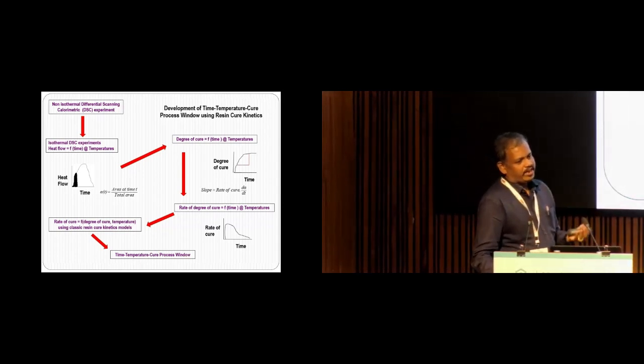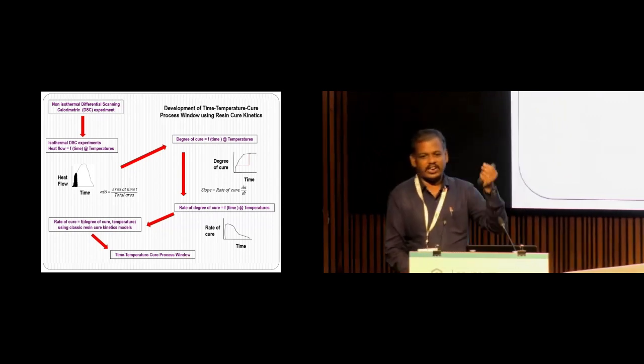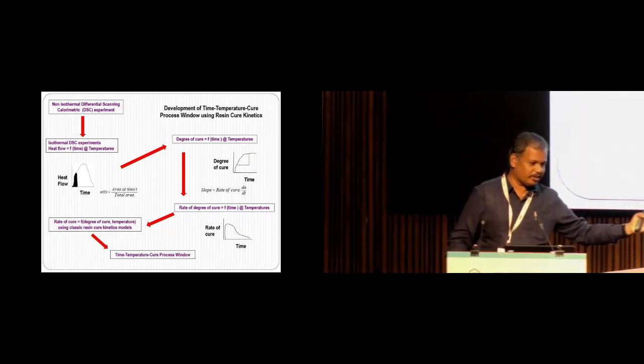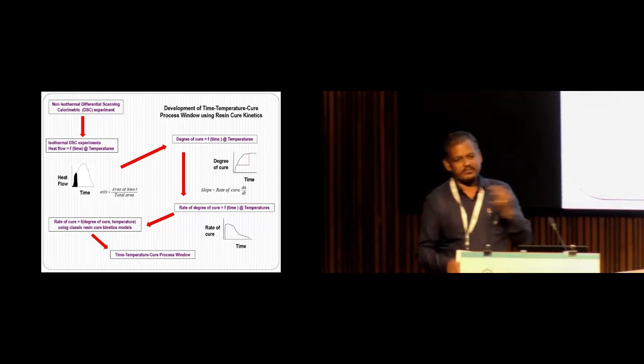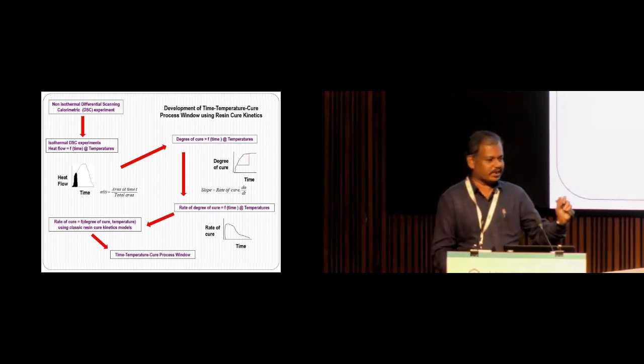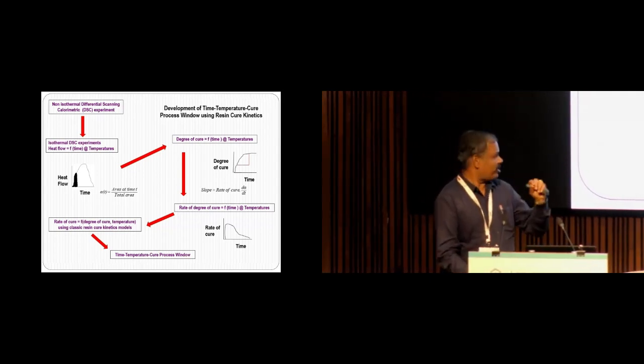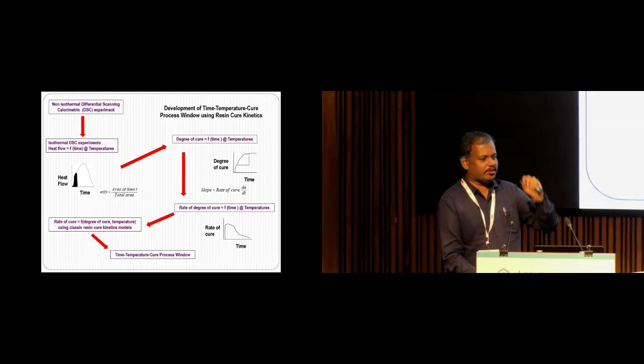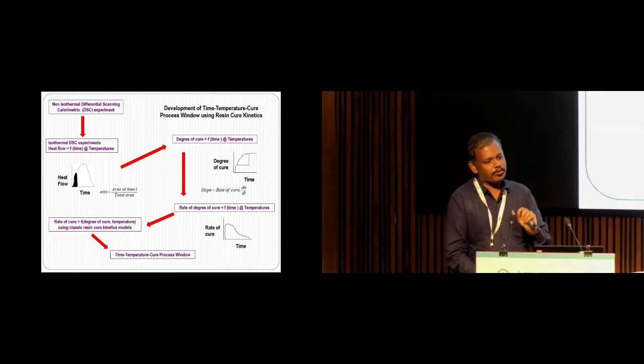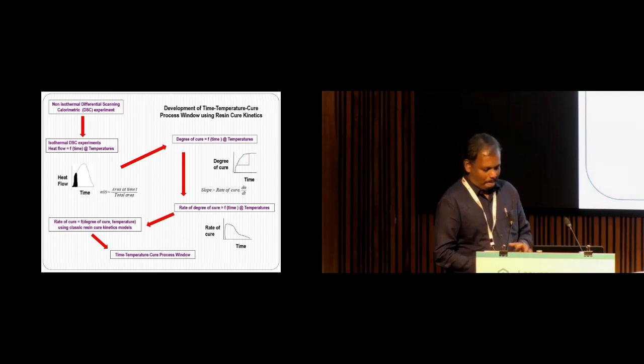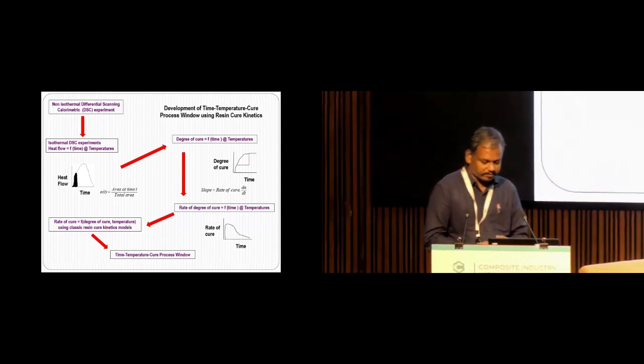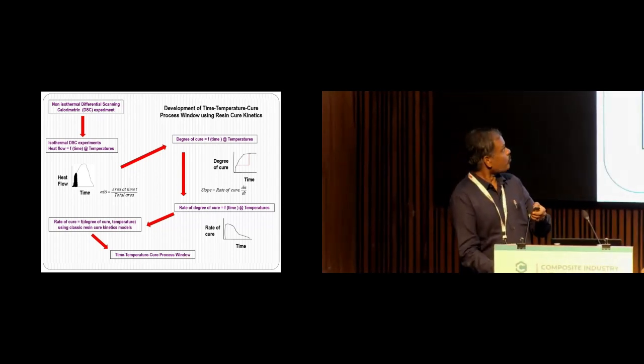From the curing kinetics modeling, you have to extrapolate the kinetic parameters from the lower end temperature to the higher end temperature, where the temperature zone is prescribed for your resin. You can extrapolate those parameters and you can produce a time-temperature cure window for any type of resin. Let me see how it is developed for RTM6 resin.